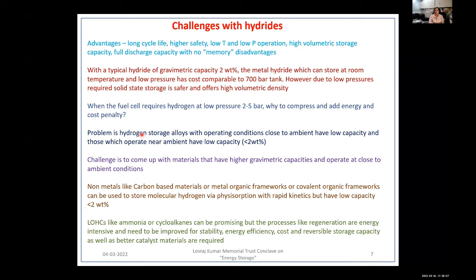They can also store hydrogen by physisorption, and they have very good kinetics, kinetics of uptake and release of hydrogen. But the problem is their capacities are less than 2 weight percent. At the same time, because the bonding is very weak, the temperature required is lower, 77 K or close to that.